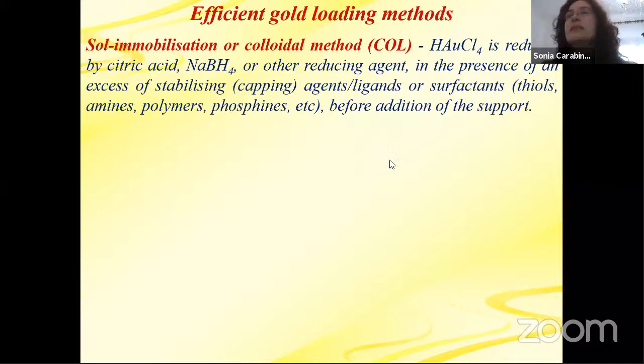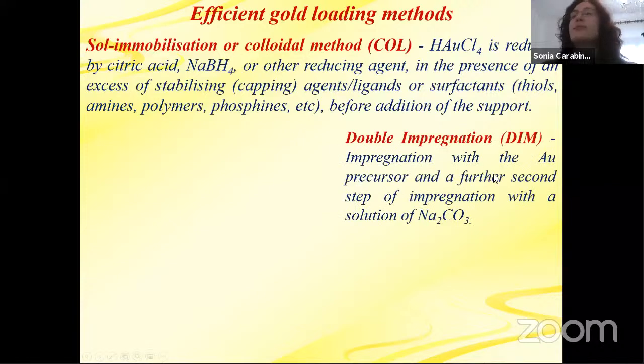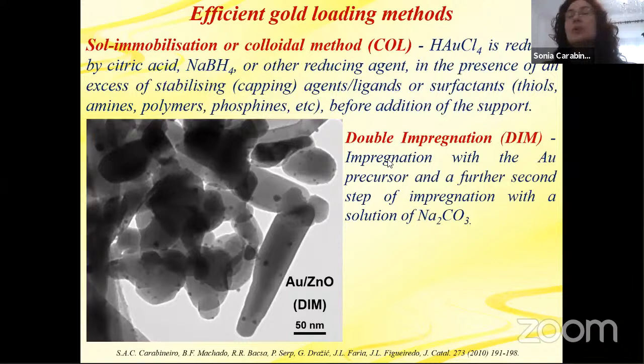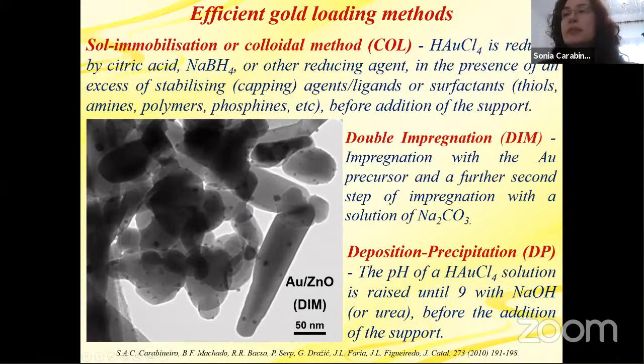There is the double impregnation method, in which the support is impregnated with the gold precursor and further with another solution of, could be sodium carbonate, and the idea is to remove the chloride. So the sodium chloride is removed by washing. And here we have a good example of gold on zinc oxide prepared by DIM. So you see here very small gold nanoparticles everywhere. And finally, there is the deposition precipitation method, in which the pH of a solution is raised until 9 with sodium hydroxide or urea before addition of the support. And there are other gold methods, but those are the ones I selected today and the ones I will talk about, the ones I used, catalysts prepared with these methods for the presentation today.